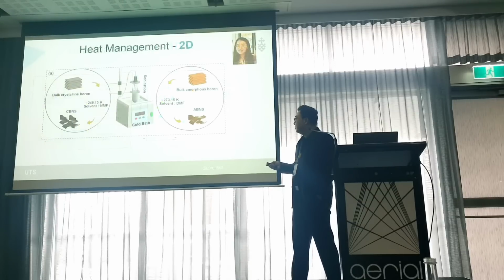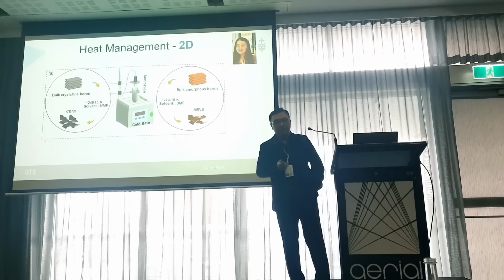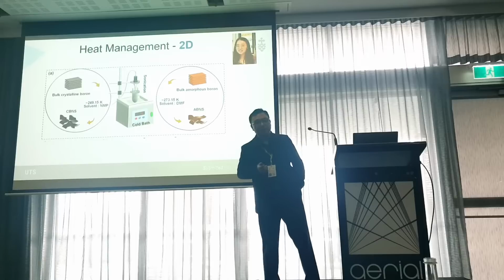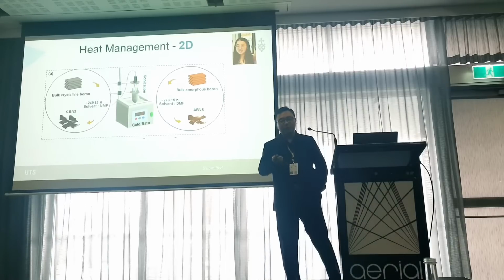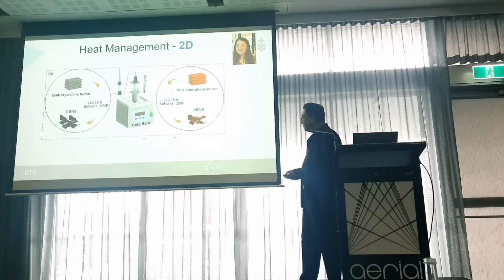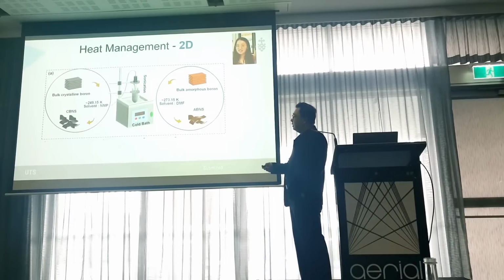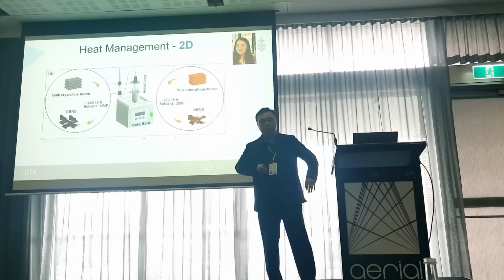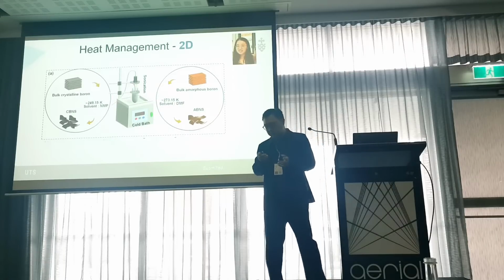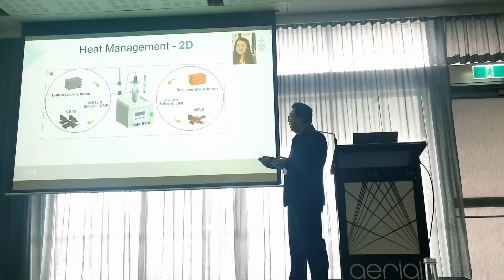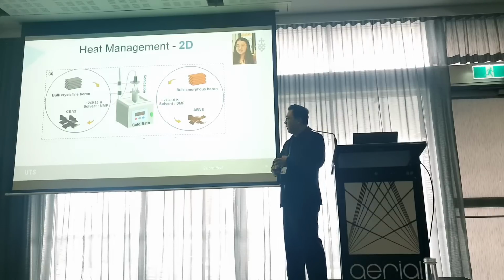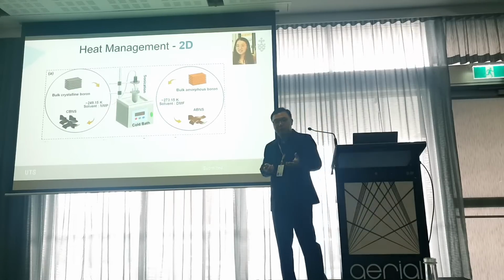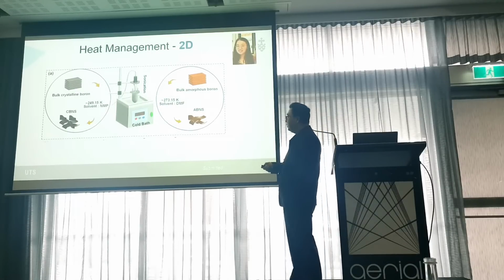Okay, so in the next study, my student Stella synthesized 2D photothermal materials. We use the bulk crystalline boron or bulk amorphous boron as the raw materials, and through a normal cold bath assisted sonication technology, we can successfully exfoliate these materials and obtain the crystalline boron nanosheet or amorphous boron nanosheet respectively.